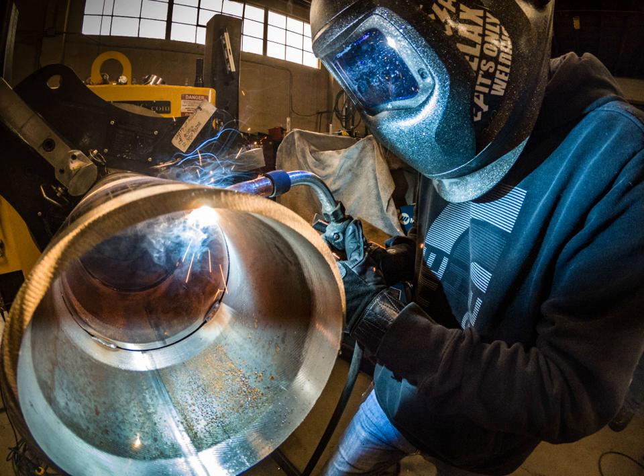Glass can also be welded to metals and ceramics, although with metals the process is usually more adhesion to the surface of the metal rather than a commingling of the two materials. However, certain glasses will typically bond only to certain metals. For example, lead glass bonds readily to copper or molybdenum, but not to aluminum. Tungsten electrodes are often used in lighting but will not bond to quartz glass, so the tungsten is often wetted with molten borosilicate glass, which bonds to both tungsten and quartz.